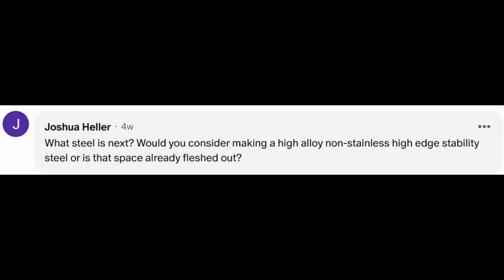Okay, that's a lot of terms. High alloy, that means that it has significant amounts of chromium. The alloy content is greater than 5%. Non-stainless, the chromium is not so high that it's a stainless steel. High edge stability steel.